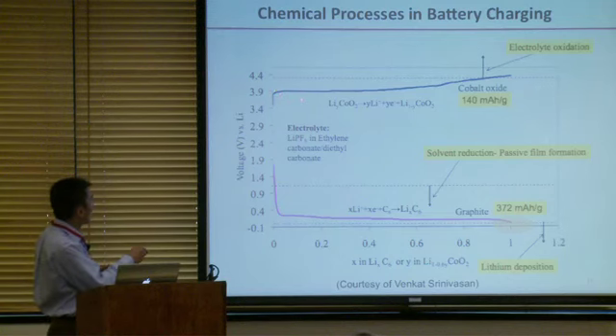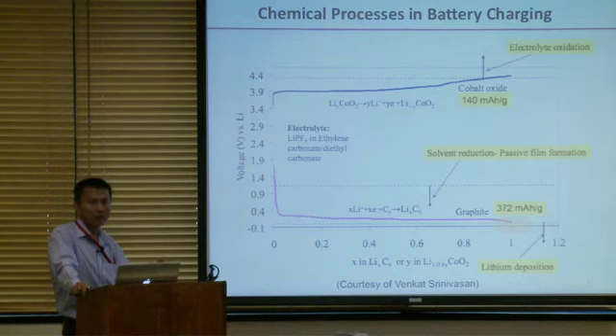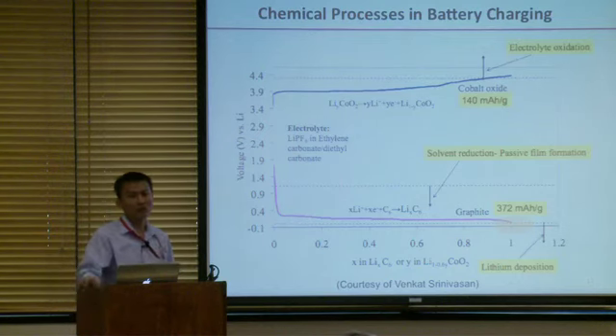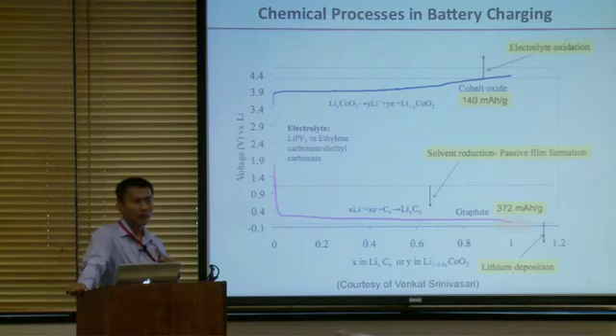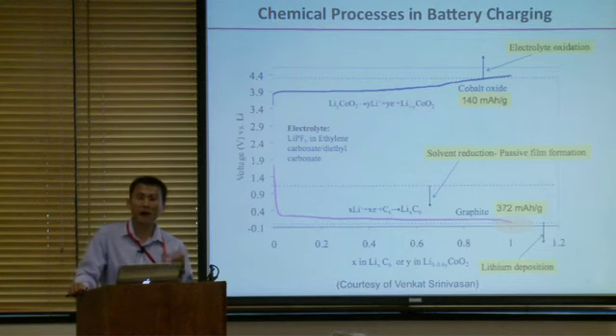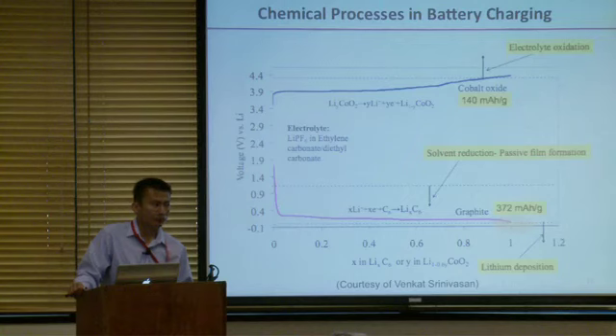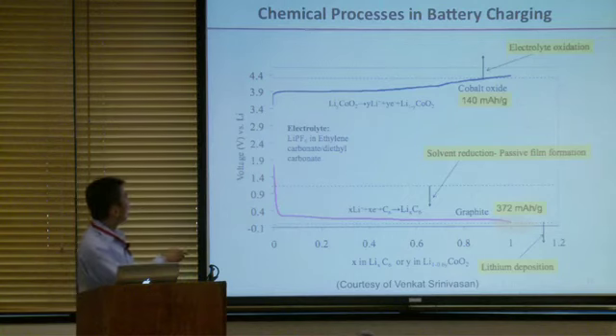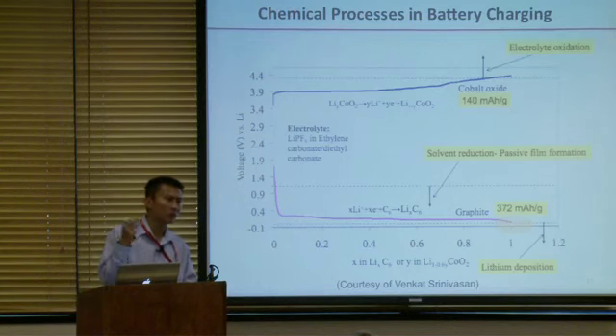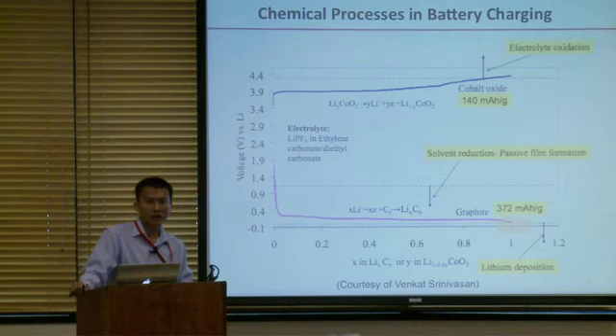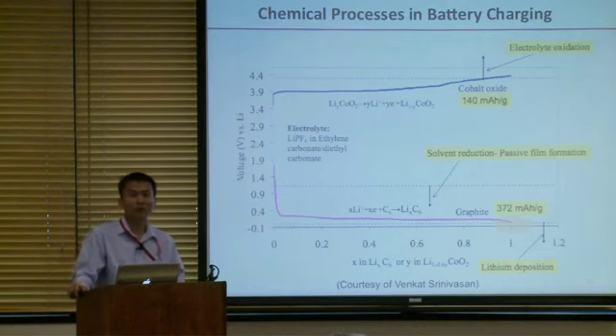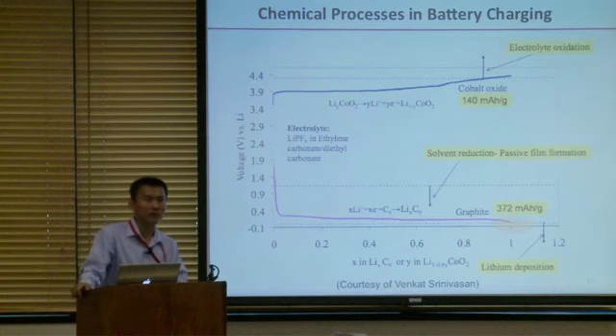The other side, lithium cobalt oxide, during the charging process, you take lithium out and put it into carbon. This becomes less and less lithium. The potential goes higher and higher. But there's a limit right here, around 4.3 volts also, above that, you start to oxidize the organic electrolyte in your batteries. And once you have an oxidation reaction happen, we know that's an energy generation reaction. And your battery heats up. And once it heats up to about 250 degrees C also, for lithium cobalt oxide, it's not stable anymore. It starts to release oxygen. Keep giving out oxygen. Now you have more oxygen coming out. It's going to oxidize more of this organic solvent, release more heat. Now it just accelerated. It's going to explode the batteries.